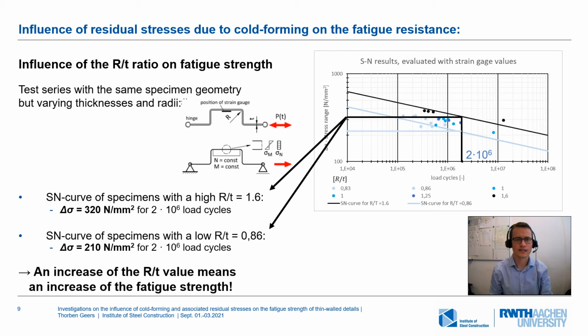First of all, I would like to discuss the influence of the ratio between radius and thickness. A series of samples with the same global geometry but different radii and thicknesses was examined. This leads to the same load, but the increased stresses in the notches show different strength on a cyclic load.